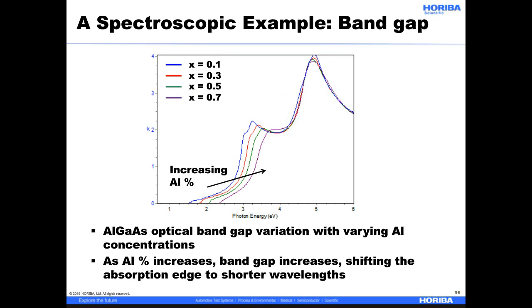Another use of the UV is for bandgap, and AlGaAs as well. The aluminum gallium arsenide optical bandgap varies with varying aluminum concentrations. As I increase the percentage of aluminum, my bandgap increases, shifting the absorption edge to shorter wavelengths. So I can see from different compositions how the optical constants can vary.